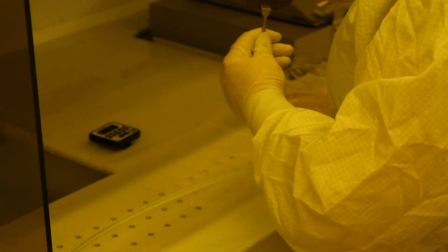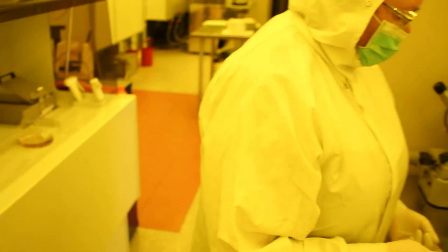When blow drying wafers, it's always good to do a center to edge spiraling motion in order to keep the solution being pushed off to the edge of the wafer. This reduces the amount of dried material that could actually occur in the patterned area of the wafer. Once the wafer is completely blow dry, you can see the pattern in the resist very easily once the unexposed resist has been removed. Now it's time for inspection.